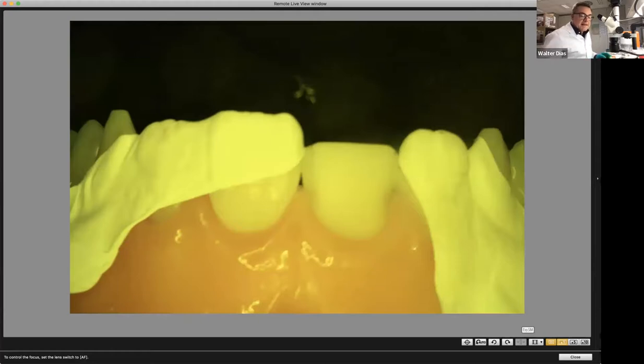And this is a technique that is becoming more and more popular nowadays. Most systems are recommending that we pre-cure the adhesive. Why? Because you have much higher bond strength. They're not stupid. And with the technique that I showed you, you can ensure that you have no excess that will prevent the fit of the veneer into the preparation. Is that clear? So the technique for adhesive application that I showed you is very good for immediate dentinal sealing, but it's also amazing for the cementation.